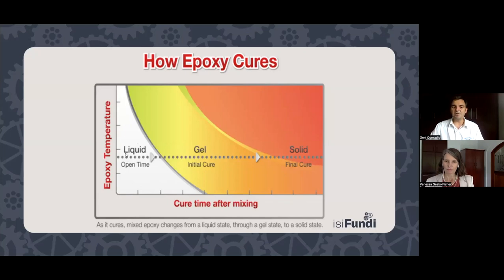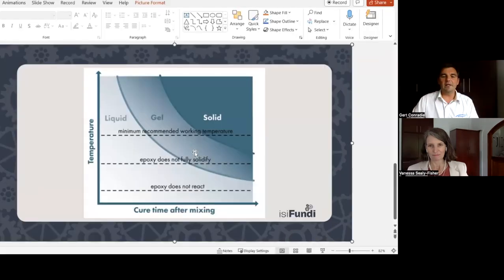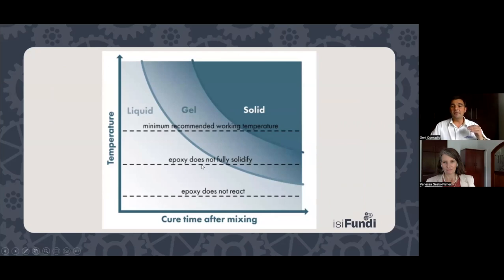For an epoxy system, it goes from a liquid to a gel to a solid state. And as you can see on this chart here, as you increase temperature, you decrease the actual time that it takes. So what we're looking at here is your actual minimum times required versus your requirement as per the technical data sheet. Again, it's that exponential negative chart that you're looking at. The higher the temperature, the shorter the time. And this is very important to note here.